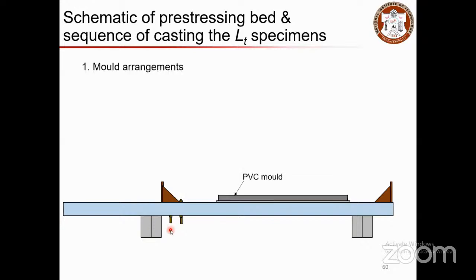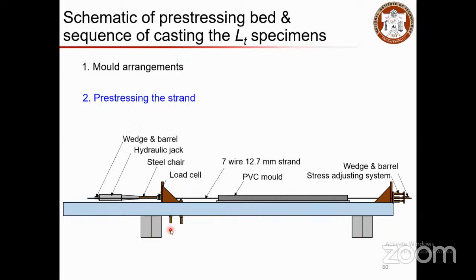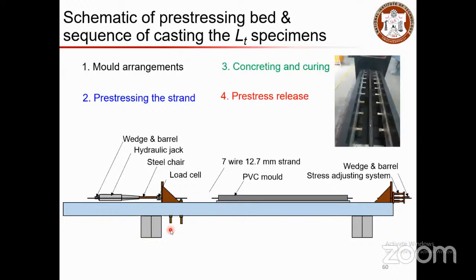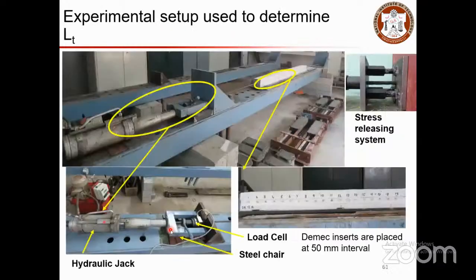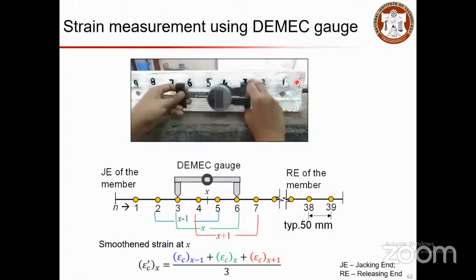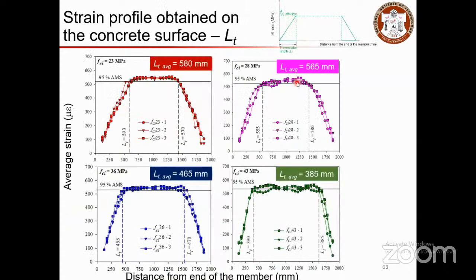You have a pre-stressing bed, and you have a mold placed. Then you pre-stress the strands using the hydraulic jack and other accessories required to activate the stresses, and you cast the concrete and cure it. Then you cut the sample. And in this method, I placed inbuilt Demec pins, which are required to measure the strain on the concrete surface. You will not be measuring the strain directly; you measure the change in distance and then calculate the strain. So these are the ways that strains are obtained.